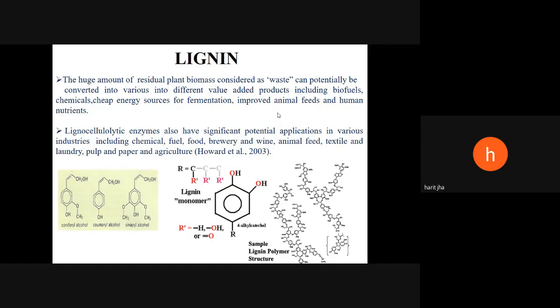This was what we have studied during my work in the PhD. So my aim was to break the lignin, to utilize the lignin in such a manner that it is removed from the system, and the pure cellulose can be utilized. We have also tried the hemicellulose, especially the xylanase, because xylanase also forms a kind of link between cellulose and lignin. And by breakdown of that cellulose and lignin link, we can ease the lignin removal process. So the aim was to remove lignin, to degrade lignin so that the cellulose can be further purified.